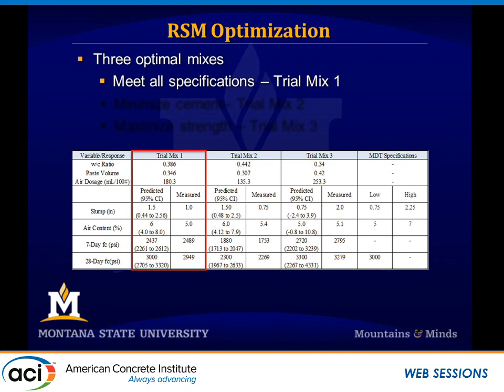So then once we got that, we came back and we performed that mix in our laboratory and measured the responses. And when we did that, we got a 1-inch slump, a 5% air, and the best for last, we predicted a 3,000 PSI concrete mix, and we got 2949, right?